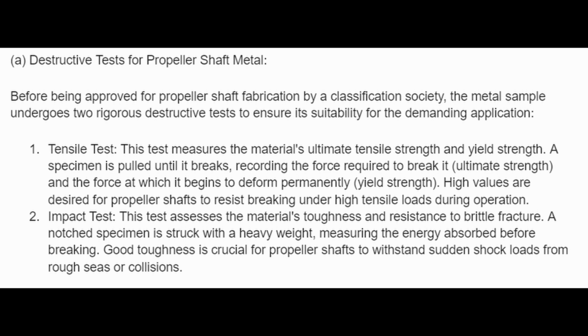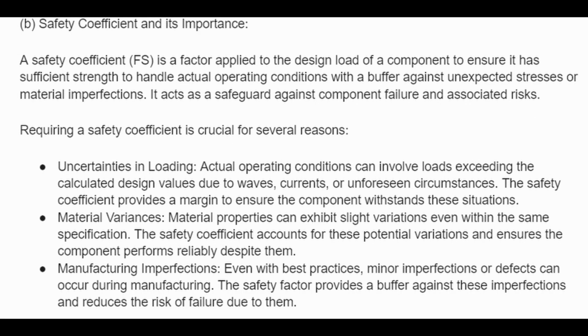2. Impact test. This test assesses the material's toughness and resistance to brittle fracture. A notched specimen is struck with a heavy weight, measuring the energy absorbed before breaking. Good toughness is critical for propeller shafts to withstand sudden shock loads from rough seas or collisions. B. Safety coefficient and its importance. A safety coefficient, FS, is a factor applied to the design load of a component to ensure it has sufficient strength to handle actual operating conditions with a buffer against unexpected stresses or material imperfections. It acts as a safeguard against component failure and associated risks.